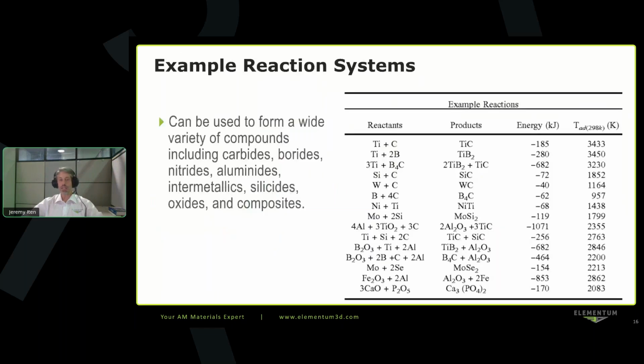Some example reaction systems that can be used with reactive additive manufacturing include all of these: titanium carbides, titanium diborides, silicon carbides, tungsten carbides, and so on. You can get into much more complicated reaction systems, nickel titaniums, moly disilicides, but also oxide and carbide or oxide and boride composites, things like that. And you can predict the energies of these reactions, as well as the combustion temperatures, the heat and the temperature that you'll get from the reactions.